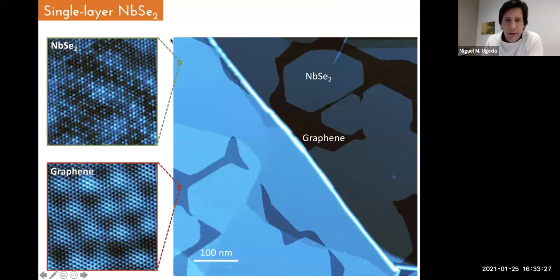Here I show you a larger scale STM image of one of our niobium diselenide samples grown on bilayer graphene on silicon carbide. So here you can see this is an island of niobium diselenide. These are other domains in an upper terrace. Typical domain of our superconductors is around 200-300 nanometers. And here on the left, you can see a couple of atomically resolved images, in this case of niobium diselenide, where you can distinguish, apart from the atomic registry, the 3x3 charge density wave superlattice.